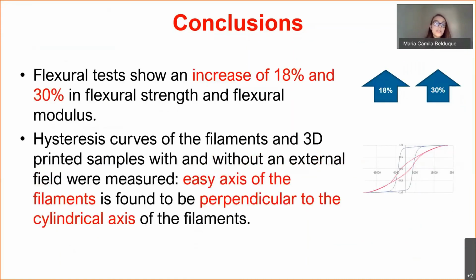Our flexural tests show an 18 and 30% increase in flexural strength and flexural modulus, respectively. Different loading levels and other mechanical properties must be investigated to determine the optimum values at which this material could be offered as an actual industry solution. And additionally, the hysteresis curves of the filaments and 3D printed samples with and without an external field were measured. The easy axis of the filaments is found to be perpendicular to the cylindrical axis of the filaments.